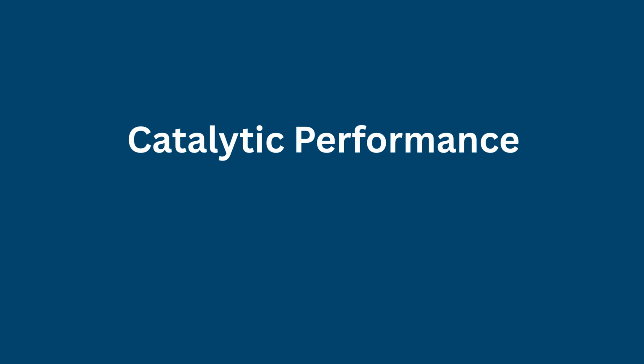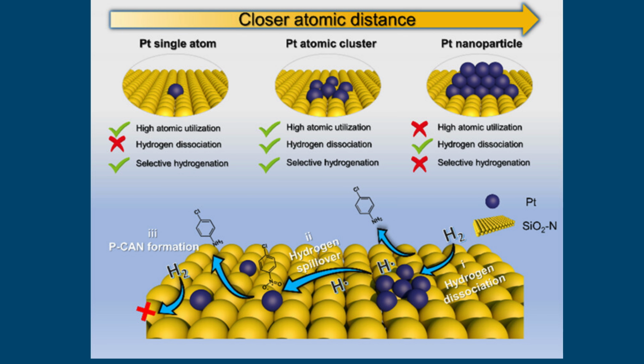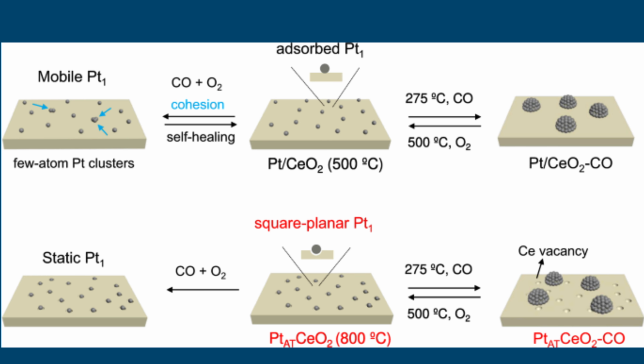Catalytic performance. The cerium oxide-supported platinum single-atom catalyst exhibits enhanced catalytic activity, particularly in carbon monoxide oxidation, a key reaction in emissions control. The improved performance is attributed to high dispersion and accessibility of Pt active sites, synergistic interactions between platinum and the redox-active cerium oxide support, and stabilization of catalytically relevant oxidation states. These features collectively enable efficient catalytic turnover while maintaining structural integrity.